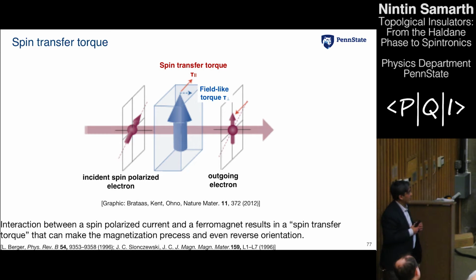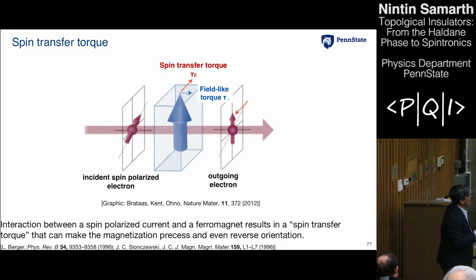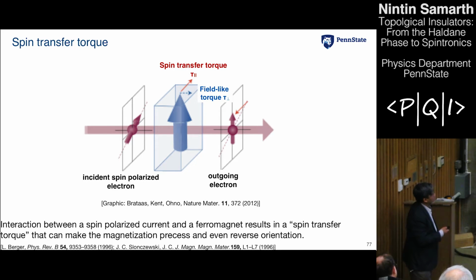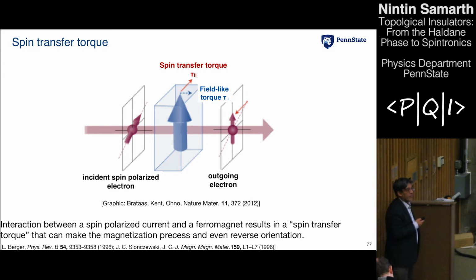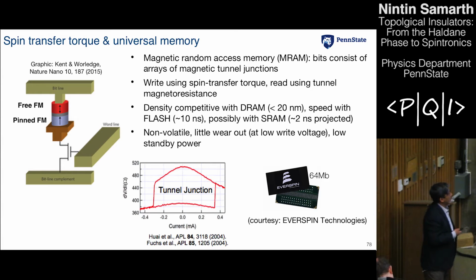So one of the interesting aspects that drove me towards these topological insulators is a concept called spin transfer torque. This is physics that you may have heard of from earlier colloquia. The basic idea is that imagine that you have some magnetized material, a ferromagnet, and imagine that you send a spin polarized electron through this ferromagnet. Without going into too many details, the essential idea is that because of conservation of angular momentum, as this electron goes through, if it's misoriented from this magnetization, then it exerts a torque on this ferromagnet, and the ferromagnet will experience a precession, or it'll get tilted because of the passage of this spin polarized electron. The reason why people are interested in this kind of phenomenon is because it leads to technologies that are quite interesting.